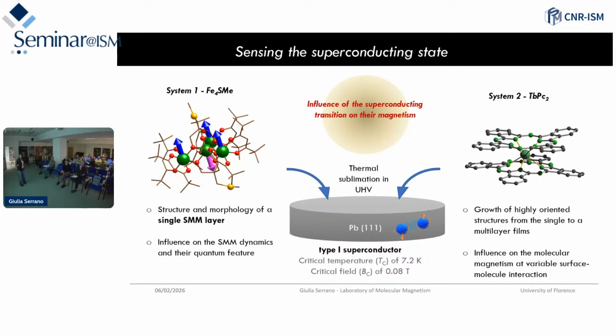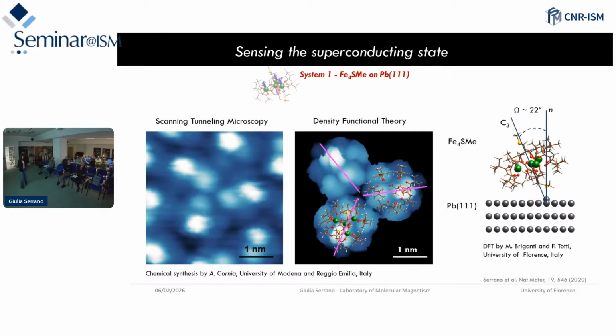As I mentioned before, I'll speak mostly about single molecule magnets, in particular this Fe4 S-methyl derivative, which has 4 iron ions with an anti-parallel spin arrangement with a total spin equal to 5. It has a large opening of the hysteresis loop in the milli-K regime. And we investigated this derivative on top of a lead-111 crystal, which is superconductor below 7 K, roughly, and 80 millitesla. To characterize this molecule, as a standard, we perform XPS characterization to confirm the integrity of the molecule, but also STM to see if this molecule can form ordered patterns on the surface.